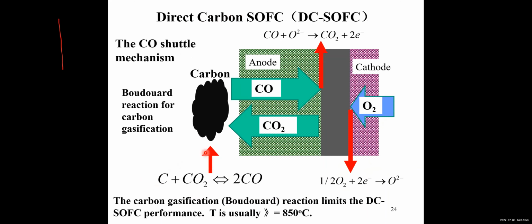When we look at the direct carbon solid oxide fuel cell, we find actually carbon cannot be directly utilized in a fuel cell, because the size of the carbon particle is quite large, about a few tens of micrometers. But the pore size of the porous anode is only about 1 or 2 micrometers. So it means the carbon particles cannot enter the porous anode, and it cannot be directly utilized for power generation.